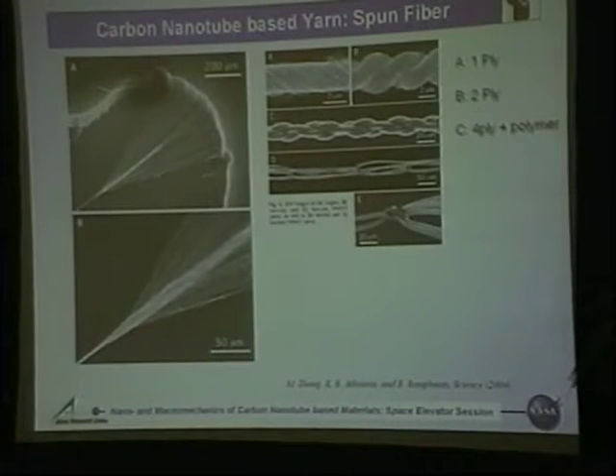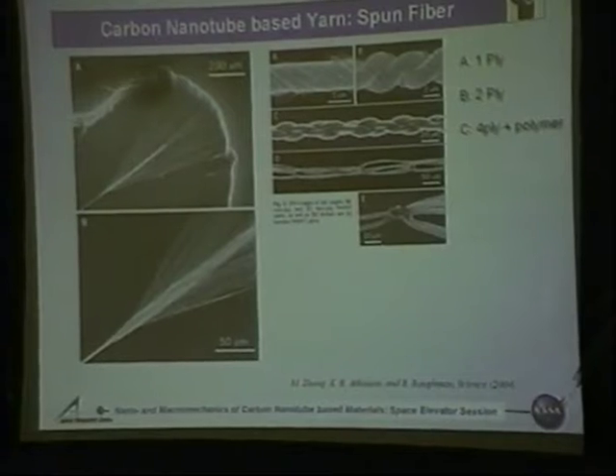But this gives you an example, and there are groups doing electro spinning and laser based spinning and so on. They have started to do it, so that as the material is growing, nanotubes are coming out in a CVD kind of process, and then you can grow them continuously. So there is hope. This is the earlier work I picked up, using that woven yarn.